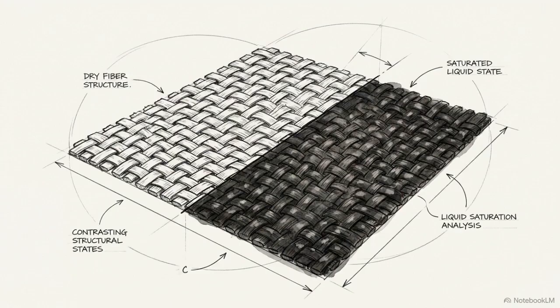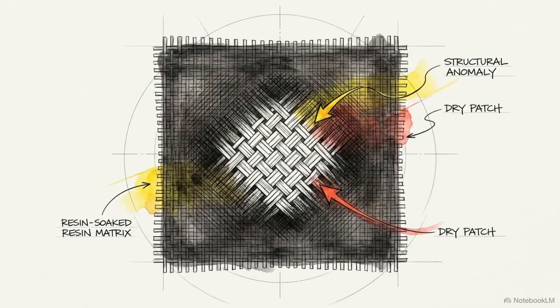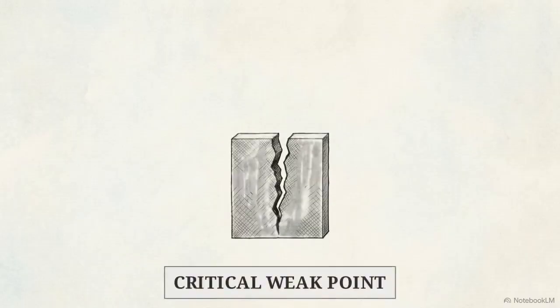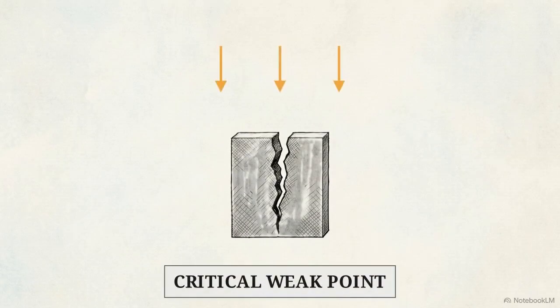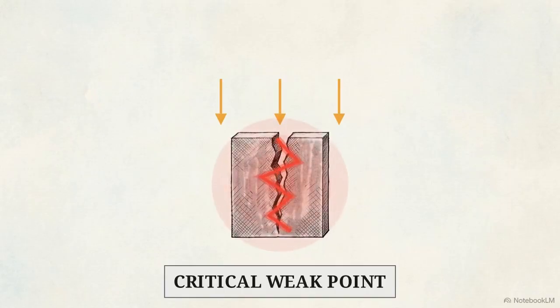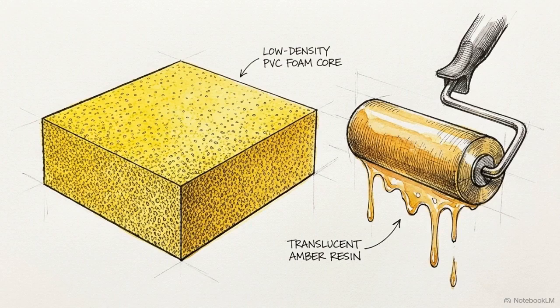You can verify this saturation with a color shift. As the resin penetrates the weave, the fabric transitions from an opaque white to a completely translucent state. Any remaining chalky white patches are dry spots. These are critical weak points that will fail under stress and destroy the panel's tensile strength. Achieving 100% translucency during this phase is what dictates the maximum structural integrity of the entire lower half of the finished composite. Once the bottom skin is wet, you prepare the central spacer.